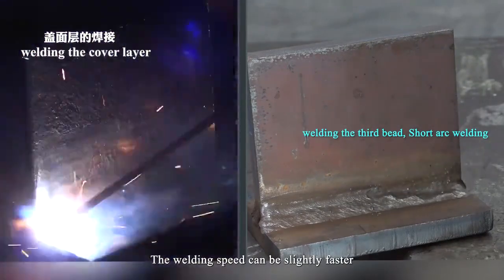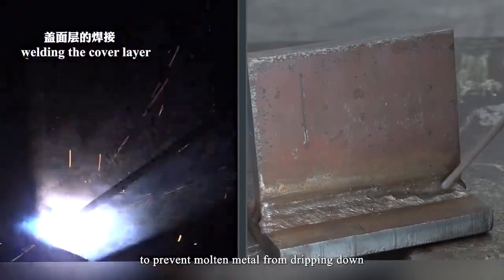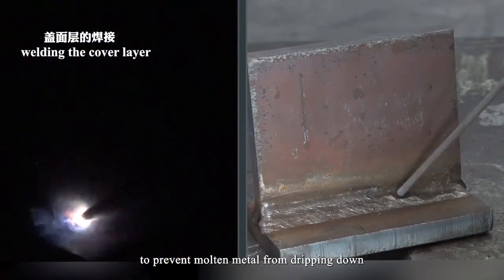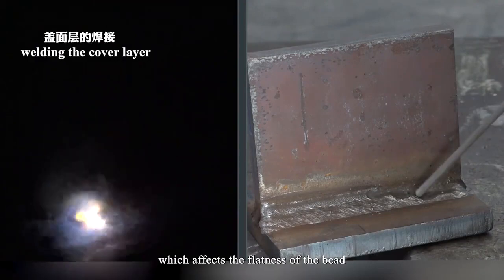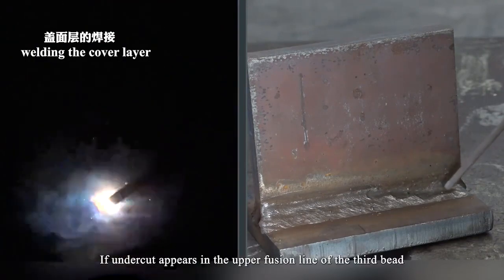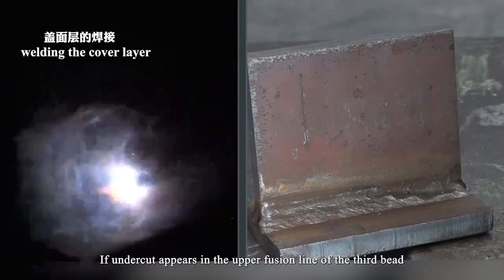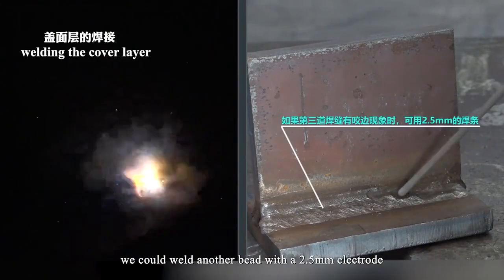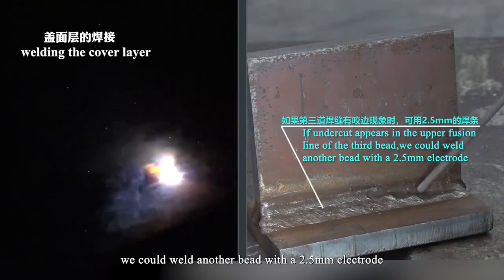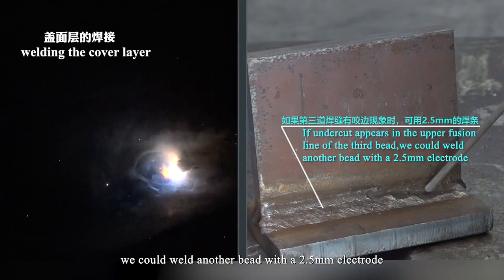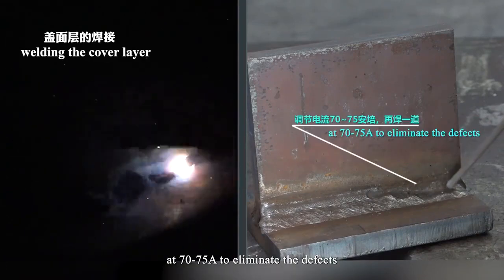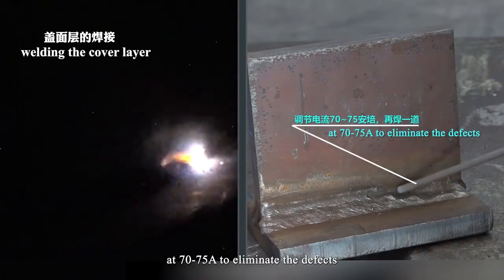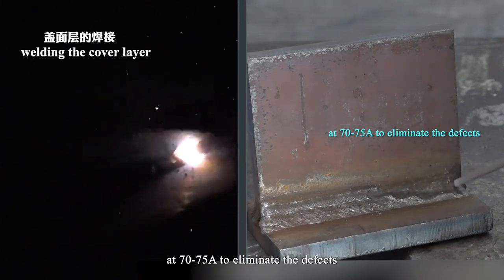The welding speed can be slightly faster to prevent molten metal from dripping down, which affects the fullness of the bead. If undercut appears in the upper fusion line of the third bead, we could weld another bead with a 2.5 mm electrode at 70 to 75A to eliminate the defects.